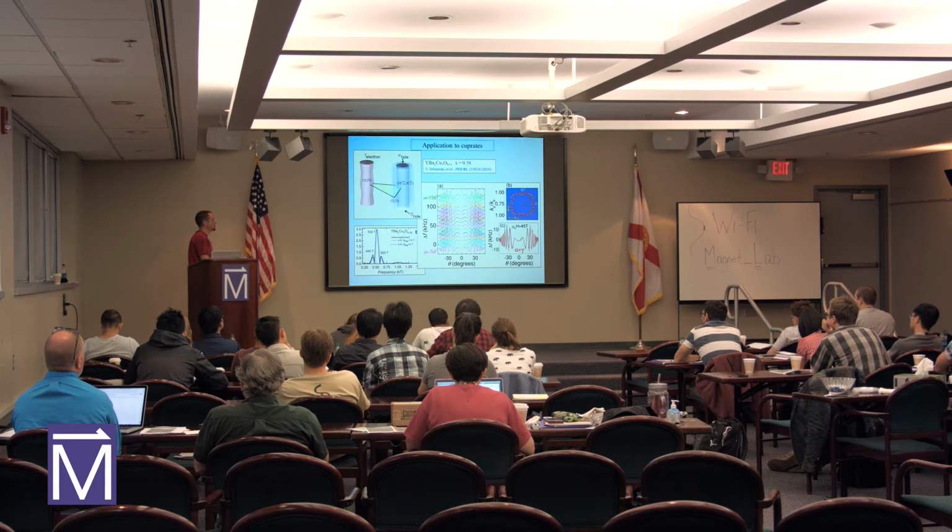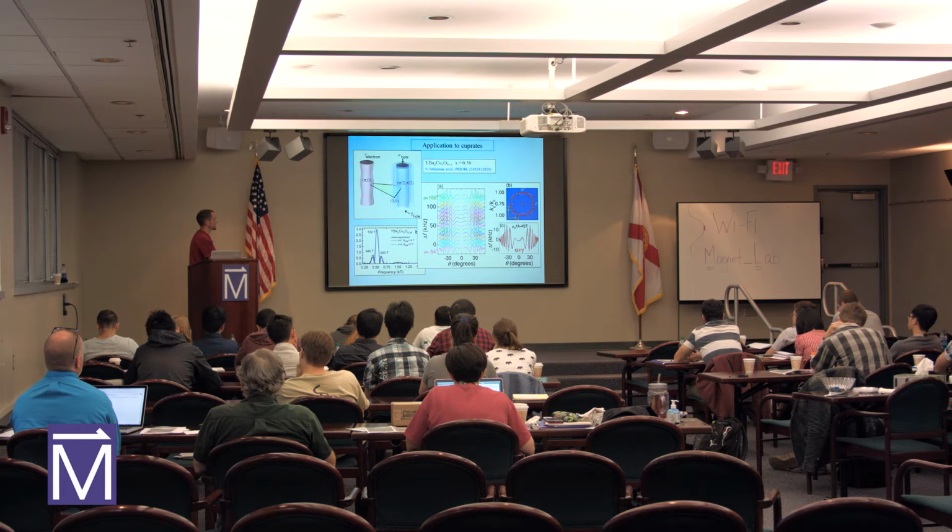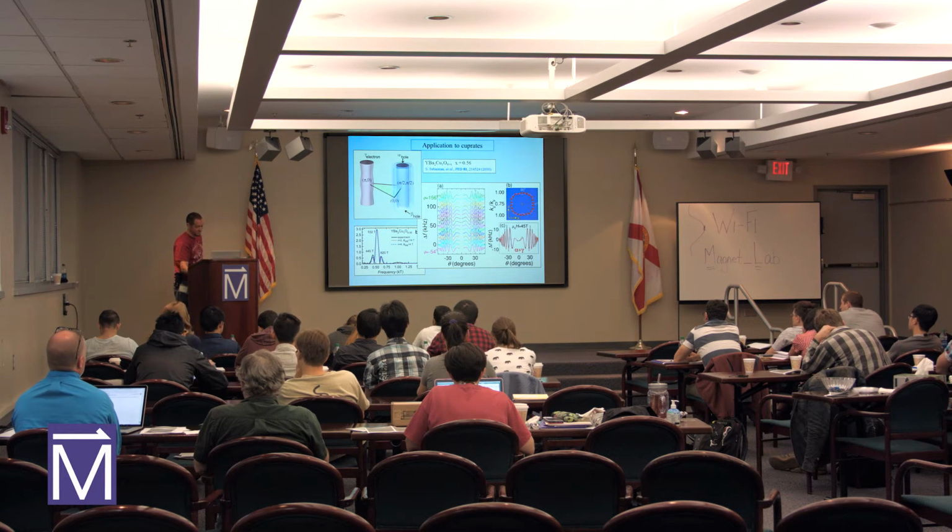Because you can only learn about the Fermi wave vector from corrugated or warped two-dimensional Fermi surfaces, when they mapped out this Fermi wave vector, they knew it was from this gamma orbit. They had an idea ahead of time of what the gamma plus the alpha orbit would look like. This black and red trace is the actual data compared to a model of what the Fermi surface should look like. So this AMRO data is a powerful technique as long as you have a corrugated two-dimensional Fermi surface and not just a two-dimensional cylinder.